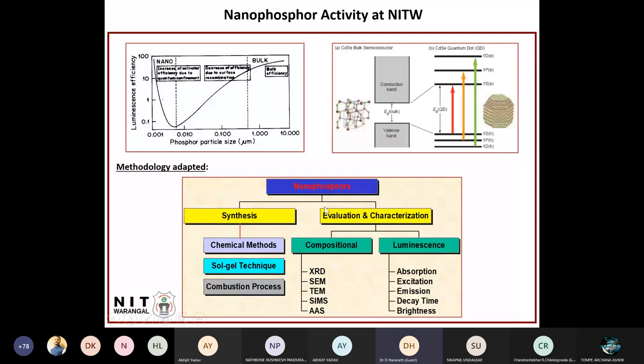For evaluation and characterization, we do both compositional evaluation and luminescence evaluation. For compositional evaluation, we go for XRD for structural determination, SEM and TEM for morphology determination, SIMS and atomic absorption spectroscopy for elemental analysis. There are various techniques to check whether we really got that material or not. For luminescence characterization, we measure absorption, excitation, emission, decay time, and brightness. These are the things we usually carry out in our laboratory.